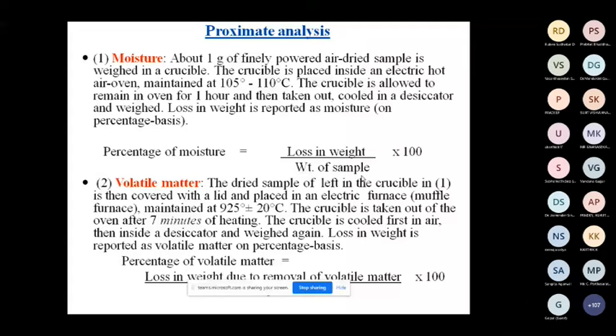Then take it out and find out the weight loss. Whatever weight loss occurs in 7 minutes at 900 degrees centigrade is the volatile matter. So the loss in weight due to removal of the volatile matter, divided by the sample weight, times 100, will give you the volatile matter content. So: moisture, volatile matter.